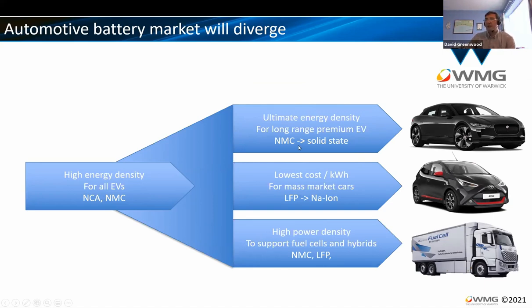And those will tend to focus on the nickel, cobalt, manganese chemistries initially, and they will probably be the first customers for solid state chemistry on the grounds that it will be particularly with lithium anodes, the thing which will deliver that kind of long range. But for much more of the cars on the market, it becomes around lower cost per kilowatt hour. So we'll start to move away from these nickel, cobalt, manganese materials and towards cheaper alternatives like lithium iron phosphate. And I think that sodium ion, actually, which Jerry Barker is going to be talking about in a moment, has some real opportunities there as well.